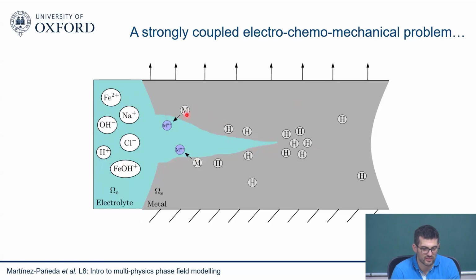There's an interface, there's a defect, some sort of defect, a pit, a crack between the electrolyte and the metal. There's a lot of things happening at the surface of that defect. You may have a corrosion reaction, so you have metal ions being detached from the metal and moving away into the electrolyte. You may have absorption of hydrogen. We discussed this in the seminar. Hydrogen comes in and travels through the crystal lattice. It's attracted to areas of hydrostatic stress. So again, everything is strongly coupled. The dissolution of metal is also impacted by the mechanical fields. You may have a passivation layer here that you're rupturing through your mechanical fields. So there's many, many things happening, all of them strongly coupled, and this is the challenge.